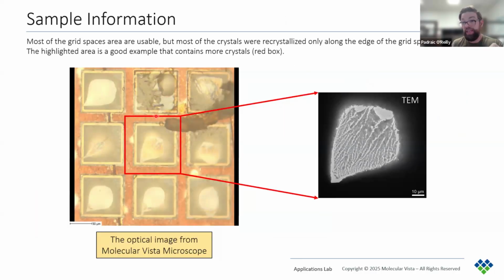So we can mount these TEM grids on AFM disks and use the grid structure then to navigate to specific crystals to measure known locations. So you can see from this TEM image that the same region of interest has been located in our microscope. I'd like to mention here actually that we recommend PiFM being carried out first because electron beams can contaminate some samples and even ablate them. Now we see this more with SEM and EDS, but it is worth noting here too.